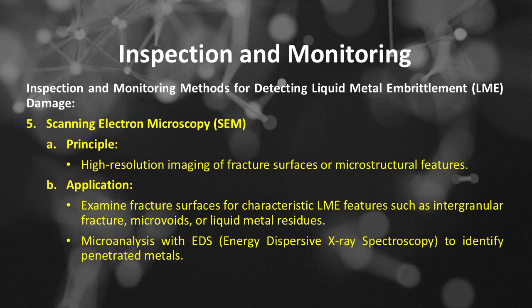Inspection and monitoring methods. Number 5 is scanning electron microscopy or SEM. Its principle is high-resolution imaging of fracture surfaces or microstructural features. Application: scanning electron microscopy is to examine fracture surfaces for characteristic LME features such as intergranular fracture, microvoids, or liquid metal residues. Microanalysis with EDS, energy dispersive X-ray spectroscopy, to identify penetrated metals.